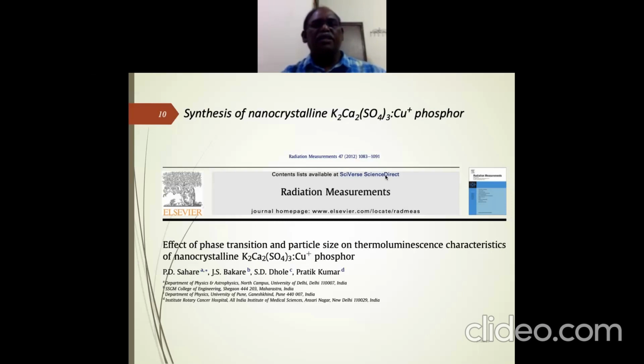But at the same time, the measurement span for radiation very much increases. Generally, with microcrystalline forms, you can measure up to around 100 gray. But with these nanomaterials, you can go up to maybe kilo gray, and in one of our materials we have also measured up to 10⁵ gray. We have found that the properties of these materials do not change by giving too much radiation, so there is not much radiation hardening, and therefore they have very good applications.